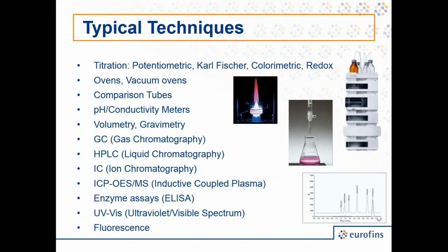In terms of some of the more typical techniques, again, the titrations are real common. There's a lot of different types. Karl Fischer for water, colorimetrics, redox. We use a lot of ovens for things. It's not real exciting, but good for driving off moisture, drying things out, getting them to where we can put them into solution, or ashing off the organics to determine inorganic content. A lot of comparison tubes, so different ampules and crucibles and cuvettes, which can then be inserted in like an instrument to look at things like UV vis. Obviously, different types of titrations.